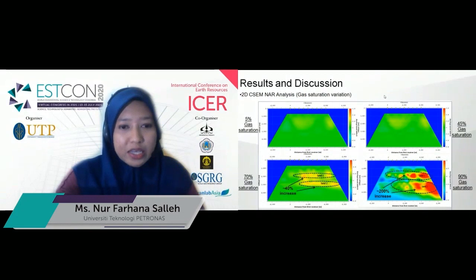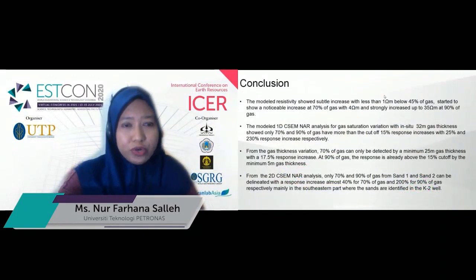So we can see the two sand layers can only be delineated by 70 and 90% gas saturations, where 70% of gas shows a 40% increase and 90% of gas shows a 200% increase. For 5 and 45%, the response is very weak and almost undetectable for all offsets. This is the conclusion for this study.